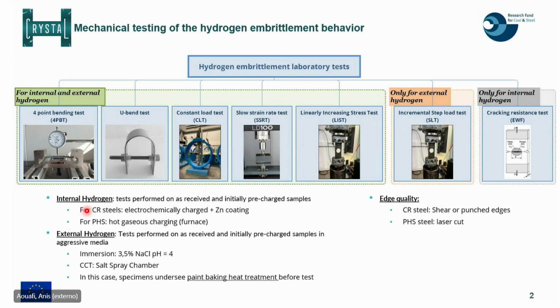What is important to highlight is that some tests have been used for both internal and external hydrogen. What is meant by internal hydrogen is to test the internal hydrogen which comes from processing of the material, or to simulate it by, as mentioned by Mélodie before, electrochemically charging the sample and putting the zinc coating in order to avoid degassing. Or for press hardening steel, we use a different condition in order to charge the materials. So some tests are used for internal and external hydrogen. One test is used only for external hydrogen, and the last test is only used for internal hydrogen.